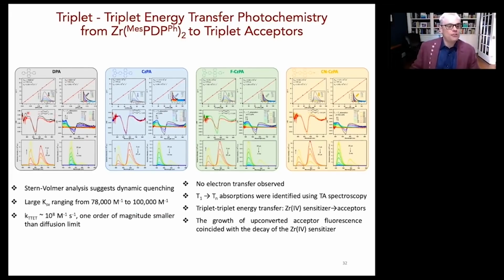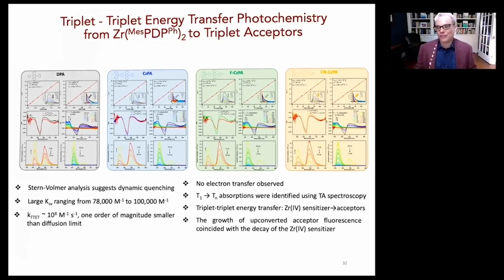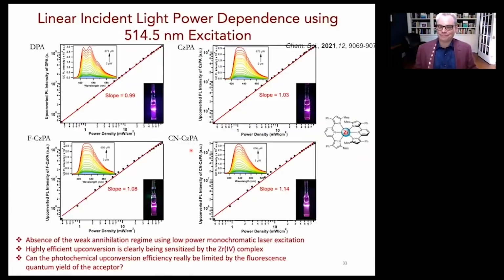You do transient absorption to prove in every single case that you're making the triplet excited state of diphenylanthracene. We know that. We do additional transient absorption experiments to get all of the parameters of the bimolecular triplet-triplet annihilation. I will not show you that data because that's just way too specialized for this particular case. And you can see that the fluorescence generated is delayed in time. So this is all classic examples of, again, sensitized triplet-triplet annihilation processes. But here's where this is different.